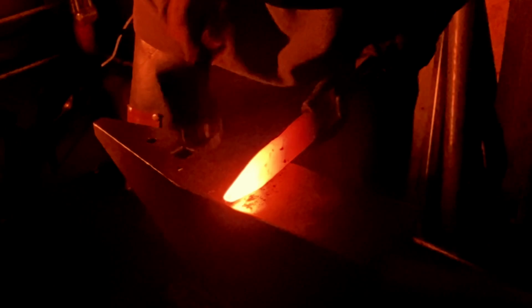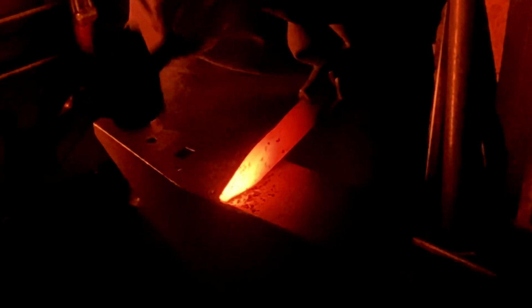Started forging at a cooler temperature. And another thing is you don't want to forge this stuff too cold. And you can really feel the material stiffen up on you. And that's a sign that your carbide content is rising. And there's a greater chance of fracturing at that point. So you really got to keep it at the right temperature when you're forging.